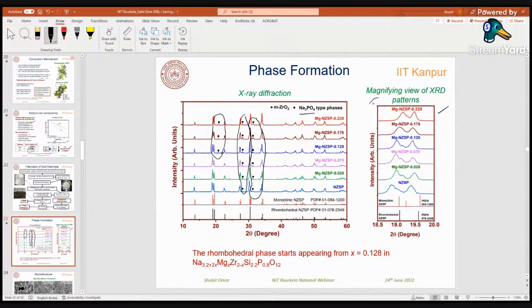This is the magnifying view of the XRD pattern, and this is the peak that I'm magnifying here, near 19 degree. You can see that in the monoclinic phase there is a middle peak present, and this middle peak is disappearing as you increase the concentration of magnesium inside the material. This disappearance shows that we are partially transforming the monoclinic phase to the rhombohedral phase. So there is a good thing about adding the magnesium: we are stabilizing the rhombohedral phase at room temperature.